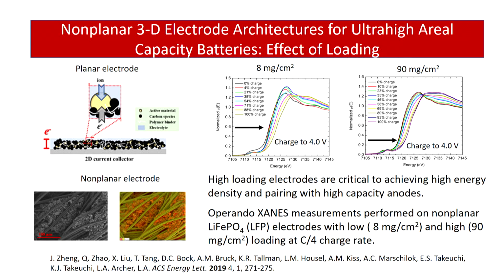The concept of non-planar and 3D electrodes is an important one. The majority of batteries today, certainly lithium-ion batteries, are made using metal current collectors and actually quite thin electrodes. And the reason is because ion transport is the limitation. But when contemplating large-scale batteries, there ends up being a fair amount of inert material in terms of many layers of metal, many layers of separator. Further, if you want to pair a cathode with a high-capacity anode, silicon, tin containing, even lithium metal, you need a very high-capacity anode. And if you simply take this 2D architecture and make it thick, you won't be able to utilize that active material.